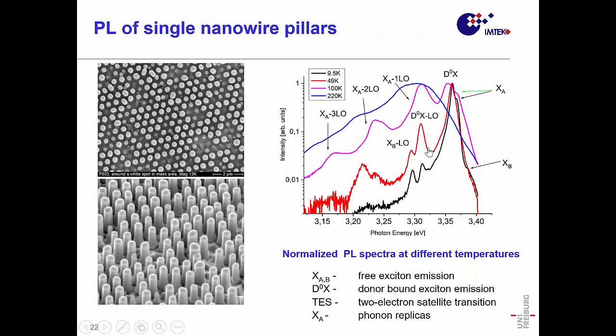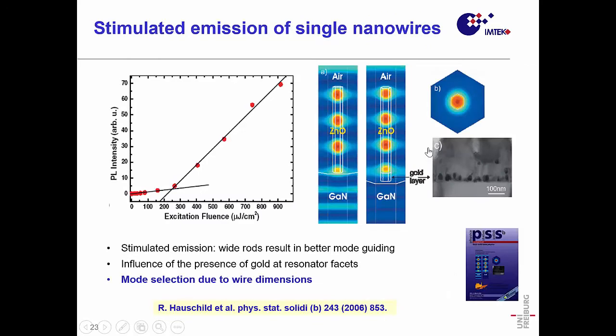And that means if you go back to this image, you see we have small variation in the length and small variation in the diameter. And that means each of these pillars has a slightly different selecting mode, a slightly different stimulated emission coming out. Of course, you can average that over large numbers, and you get an average of that. But we did it here with nanowires prepared far away from each other so that we were able to measure single nanowires for stimulated emission. That means looking into whether we could make nanolasers out of that. Okay.